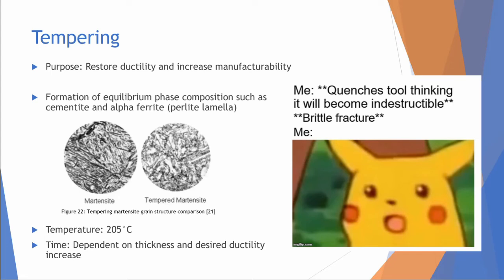Tempering of steel martensite can decompose to produce a new composition depending on the temperature. With regards to our functional requirements, the proper tempering temperature is 205 degrees Celsius for approximately an hour, which mainly produces stable alpha ferrite and cementite to increase ductility. The steel is then air-cooled and the process can then be repeated to produce the desired formability.